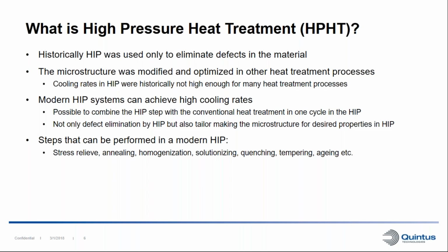So this makes it possible to combine the HIP step with the conventional heat treatment in one cycle in the HIP. So today we can not only eliminate defects by the hipping, but we can also tailor-make our microstructure to get the desired properties of the material that we want in the HIP. So we can incorporate all kinds of heat treatment steps in the HIP today. And here are some examples. We can do stress relieving, annealing, homogenization, solutionizing, quenching, tempering, aging, etc.